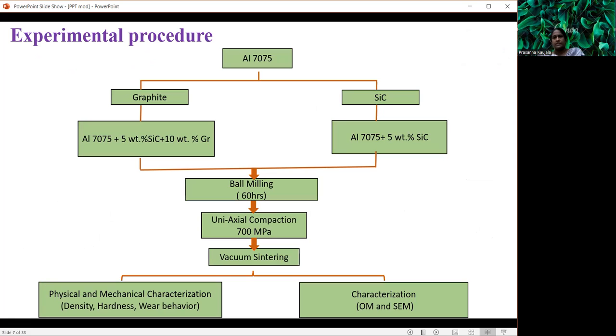The experimental procedure is that aluminium 7075 is taken, and the graphite and silicon carbide are added as powder using the powder metallurgy technique in a ball milling machine for 60 hours, and it is compacted under a pressure of 700 megapascals. Afterwards it is vacuum sintered, and then we could get the density, hardness, and wear behavior, and we could see the microstructures using the scanning electron microscope and optical microscope.